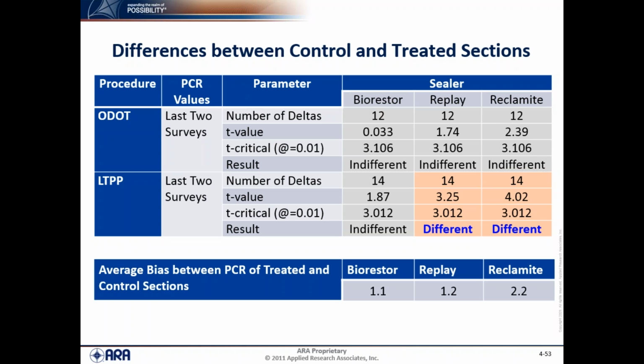This now shows the average bias, and I'll use this later on, but this is the average bias between the PCR of the treated and the PCR of the control section, okay? So the average bias for the Bio-Restore was about 1.1. The average bias on the Replay, a little bit higher, but not much, 1.2. And then the Reclamite had an average bias of 2.2. That's 2.2 in terms of a PCR value.